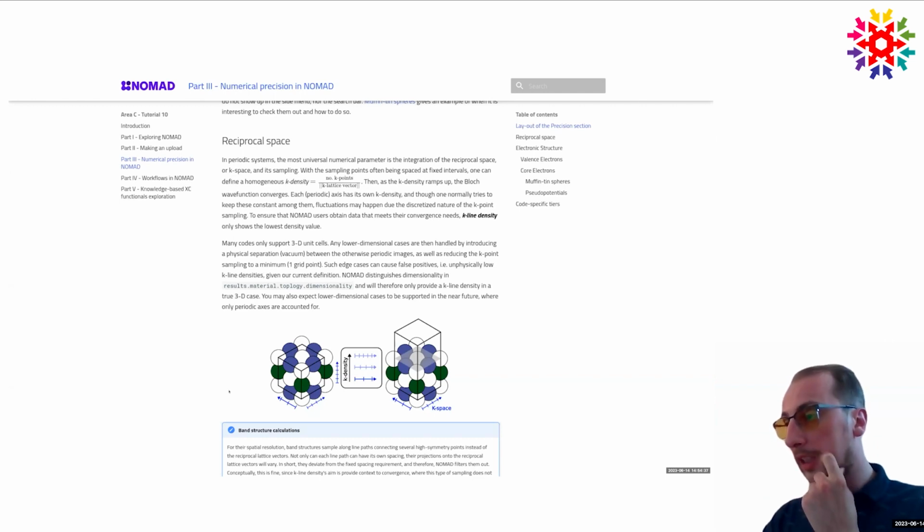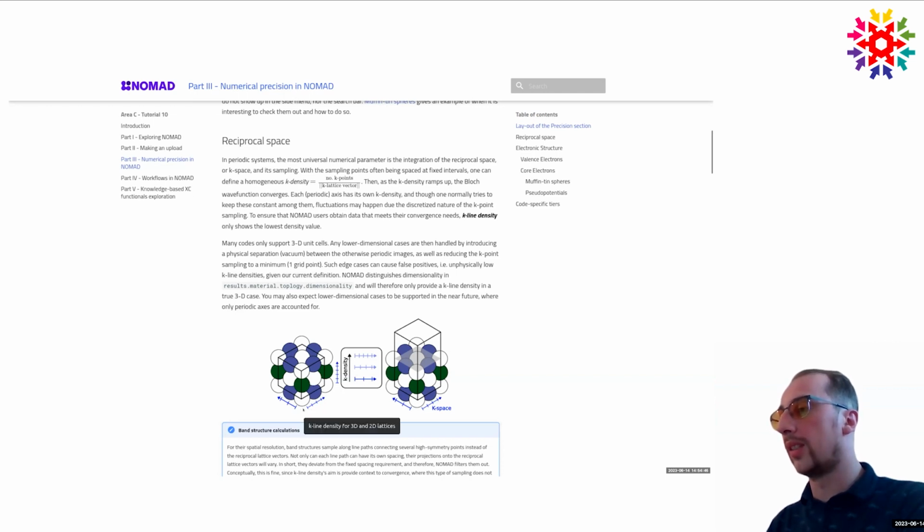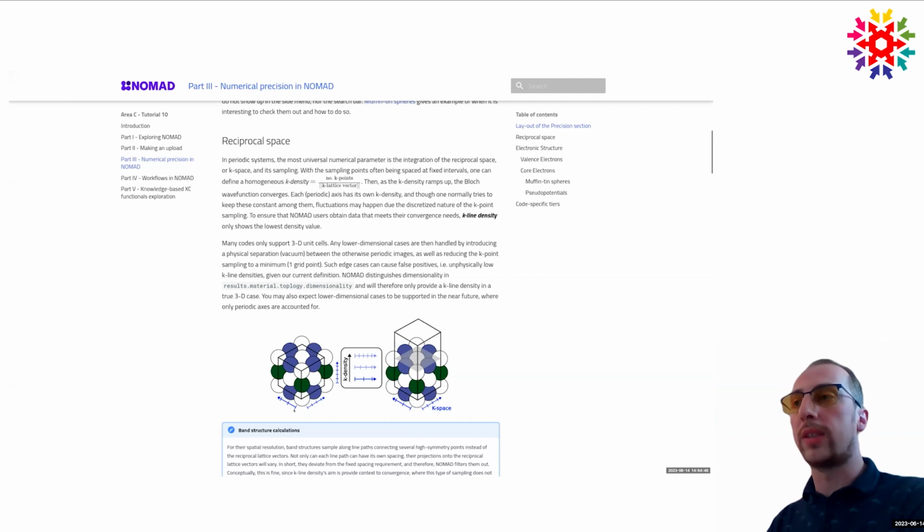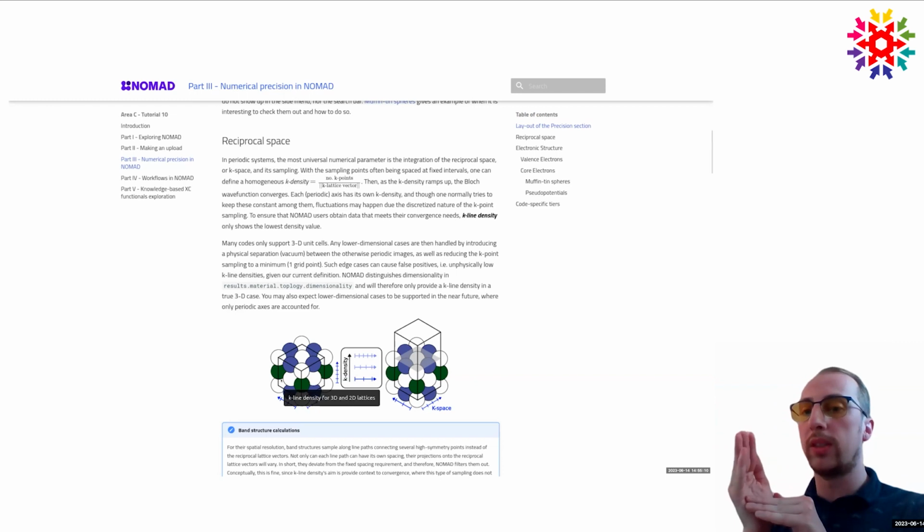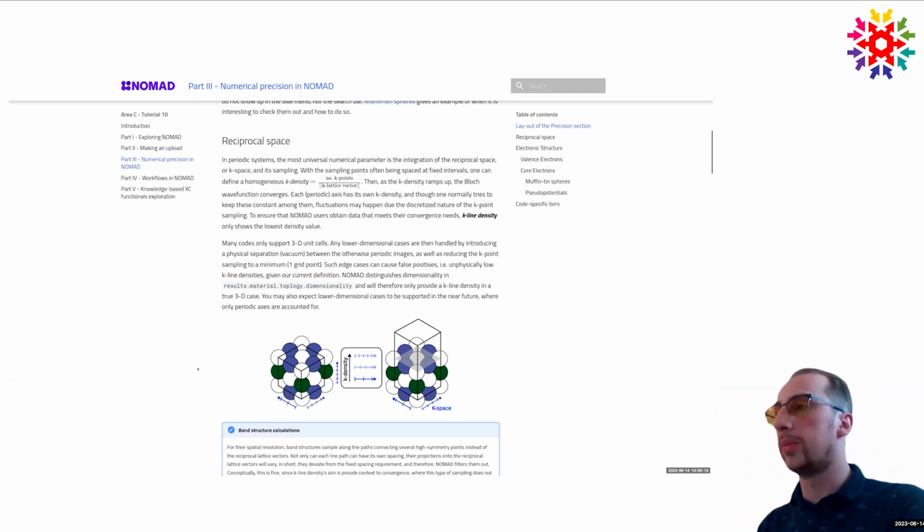So this actually takes me back to when I first started my PhD. One of the rules of thumb that they gave us is that you should make sure that this density always stays at around 30. So what they meant is we have these K-point samplings. We can see how many we are covering per unit lattice vector. And typically, you want them to be somewhat the same on all of the axes, meaning that suppose I were to double my unit cell to create some kind of supercell, I would typically halve the K-space just to have the same type of representation.